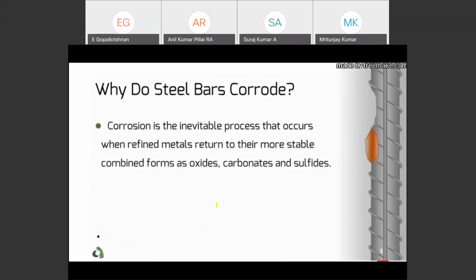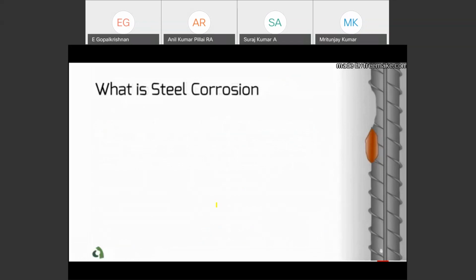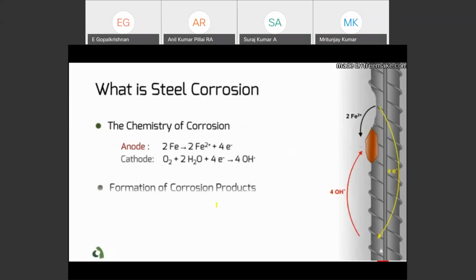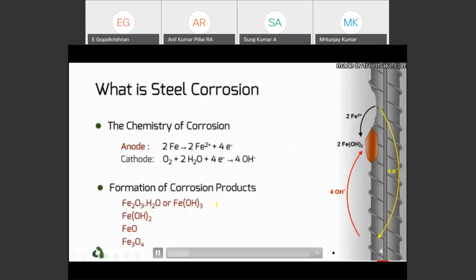For understanding, I'm going to run one small audio visual here. Corrosion is a process or chemical reaction where refined metals such as steel and iron return to their more stable combined forms as oxides, carbonates, or sulfides. In this chemical reaction, a section of the steel material acts as an anode. This means that the steel loses electrons. On the other hand, another portion of the reinforcing mesh acts as a cathode. In the cathode, oxygen combines with water and electrons to release hydroxide ions. This shows that the reactions require both water and oxygen to occur. The volume of corrosion products, especially Fe2O3, is significantly higher than the original steel. This will increase the internal pressure and consequently crack the concrete.